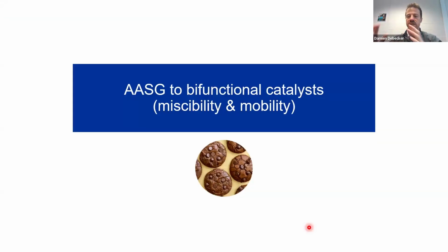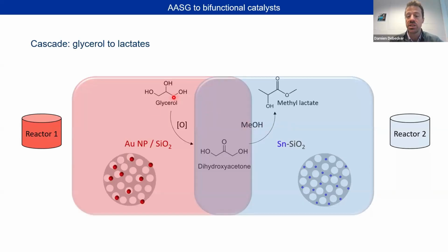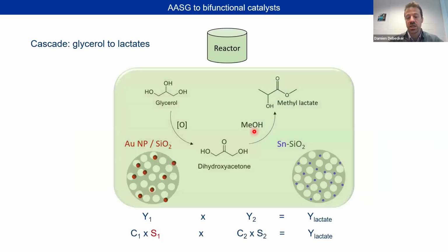We have the first reaction, the second reaction. What if we try to get a bifunctional catalyst that will be able to do both? So exploiting the two scenarios at the same time, mobility and miscibility. Indeed, you need those two reactions. If you do it separately in two different reactors, you will have a yield that is limited. And even if you do it in one reactor, you have to remember that this catalyst has a relatively poor selectivity. So of course, the final yield will be normally dictated by the relatively low selectivity of this